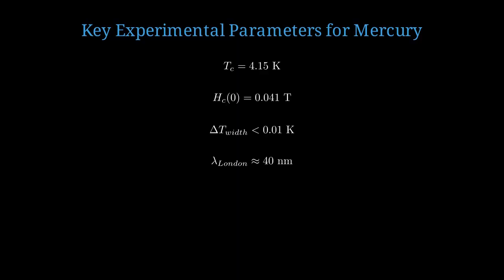Let me give you the key experimental parameters for mercury that you should remember. Critical temperature, T sub C equals 4.15 Kelvin. Critical field at zero temperature, H sub C of 0 equals 0.041 Tesla. Transition width for pure samples, less than 0.01 Kelvin. London penetration depth, approximately 40 nanometers. This is how far magnetic fields penetrate into the surface. Coherence length, approximately 30 nanometers. This is the size of a Cooper pair.